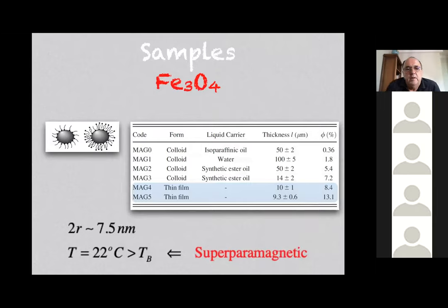And the other type of samples that we used is magnetite particles, typical diameter also about 8 nanometers, in different types of liquid carrier, for example, isoparaffinic oil, water, synthetic ester. So we have different types of coating of these particles to be carried by polar and nonpolar fluid. The idea here is essentially to take a property which is characteristic of the crystal, of the particle, not of the carrier fluid around or the molecules that we put around to avoid the agglomeration. So all the properties that we will discuss here are essentially properties obtained from the particles. The temperature is below room temperature in the winter, in Brazil, 22 degrees centigrade, and the particles are superparamagnetic at that temperature.